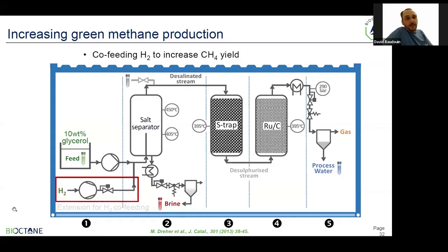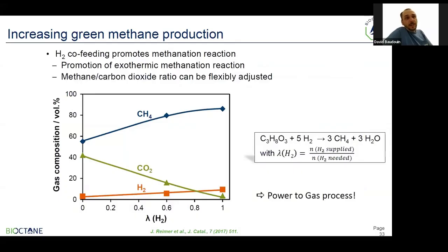Then next slide, please. Here you can find the composition of the gas as a function of the ratio of hydrogen needed to convert all the feedstock into methane. Lambda 1 means having 100% of the hydrogen needed to convert all the glycerol into methane. You can see that we do not reach 100% yet, but we are getting very close. That is a very good approach for a power-to-gas process, in a scenario where hydrogen is produced with renewable resources. Instead of storing and compressing hydrogen, which is expensive, it can be used directly.